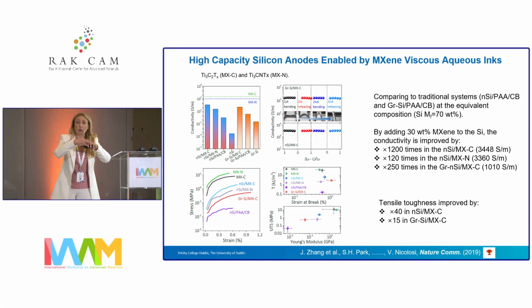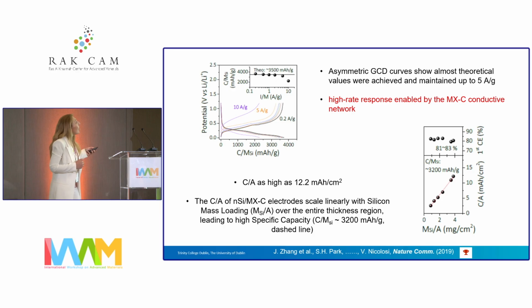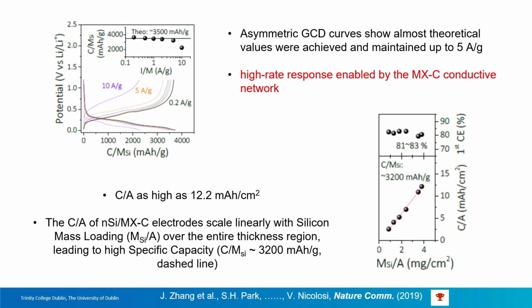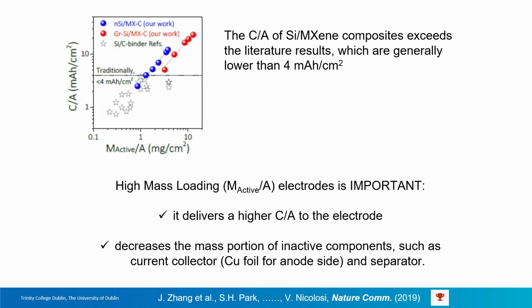And this also becomes resistant to bending. The other advantage is in the mechanical properties of the electrode. We could improve the tensile toughness of the electrode between 15 and 40 times. From there, we went to look at the electrochemistry. If we look at the electrochemical performance, we can get a very nice rate response, and this is because we have a very electrically conductive network of MXenes there. And the very remarkable thing is that we can indeed achieve theoretical capacity for the silicon particles. So it becomes a very, very important tool.